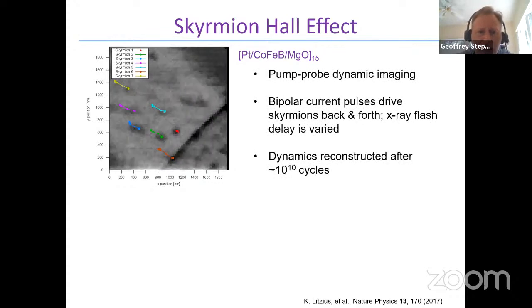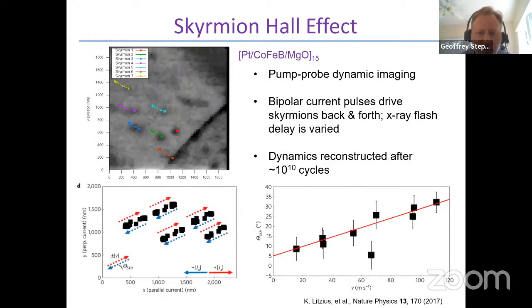And so it's very encouraging that one can drive a skyrmion reproducibly back and forth this number of cycles, because that would be very important for any kinds of device application. But if one scales this down to have racetracks that are tens of nanometers wide, of course, the skyrmion is going to run into the edge. And so this is something that's undesirable for application.